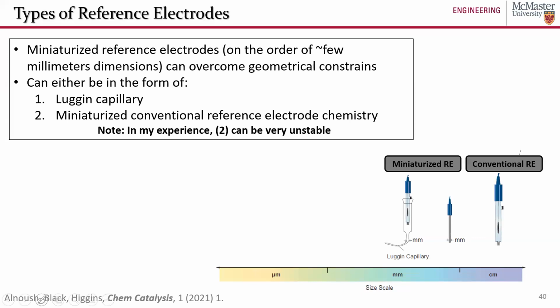Now, I'm just going to give a quick public service announcement. And if you've had different experiences, I'd love to hear about them. But I should note that these miniaturized conventional reference electrodes, these 1 to 2 millimeter silver chloride reference electrodes, can be very unstable and very unreliable. I found them drifting by as much as 300 or 400 millivolts from day to day. And so if you treat them well and all the stars align, they can be very reliable, they can be very convenient. But if you are going to use those, be careful and make sure you are calibrating them at regular intervals.